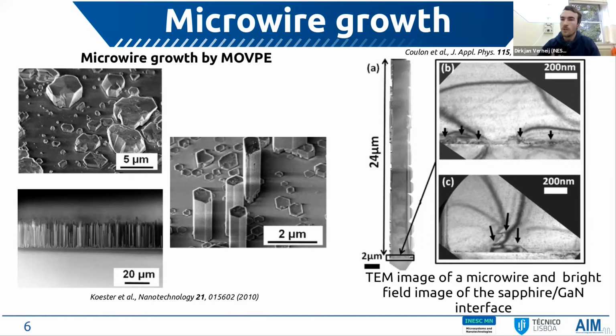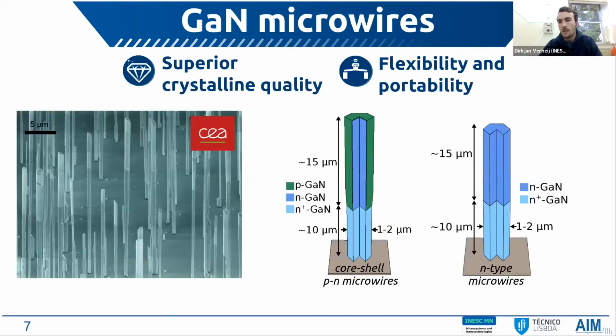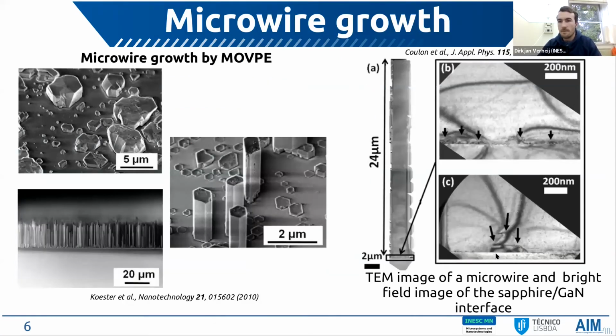Then to promote the vertical growth instead of the lateral growth, they figured out that by introducing a silane flux during the initial stage of the growth, they could suppress the lateral growth and only really promote the vertical growth. When the wires reach around 10 micrometers, this silane flux can be turned off and the vertical growth will continue in the c direction. This is actually also the reason for the different doping concentrations here. The heavy doping of the bottom part is a direct consequence of the application of the silane flux. Thanks.